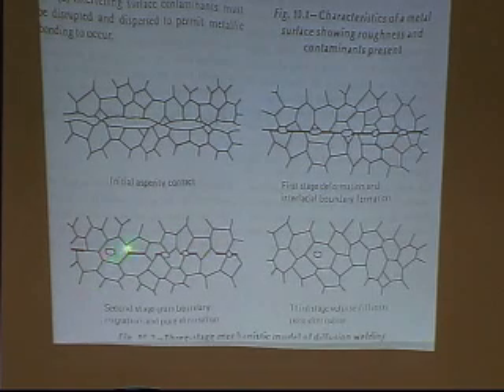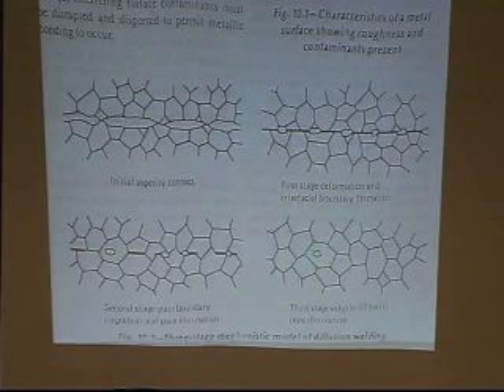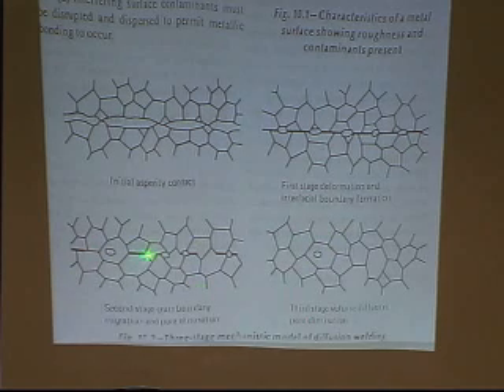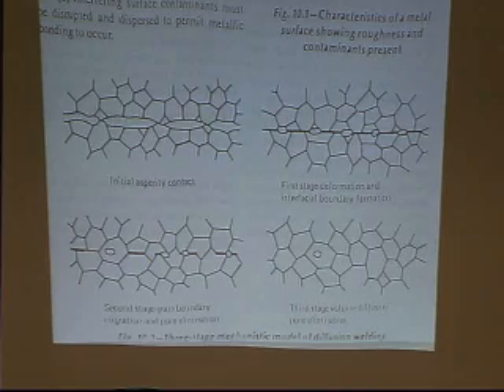So I get rid of some of the pores, but it turns out if a pore gets trapped, the third stage, if a pore gets trapped in the center of a grain and it's not in contact with a grain boundary, it'll stay there for 100 years. Oh, not 100 years, maybe 50 years at temperature. Okay? You've got to have your pores in contact with your grain boundaries because the grain boundaries are the sinks for diffusion. Otherwise, those vacancies have to diffuse all the way through that crystal lattice.